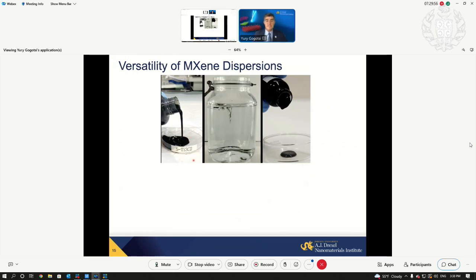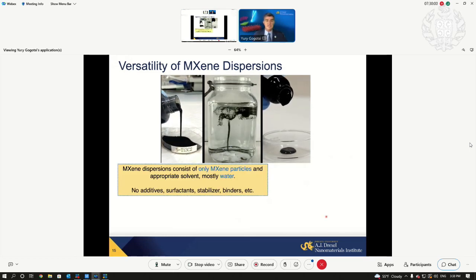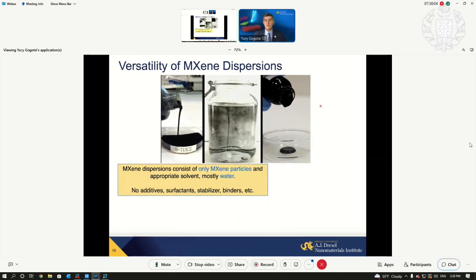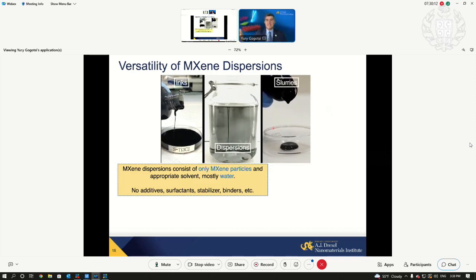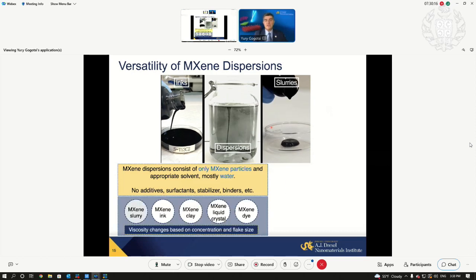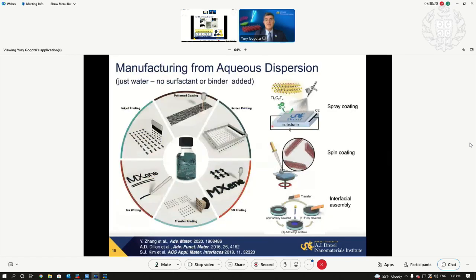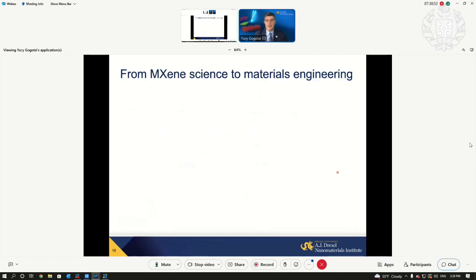And we can make it thin or thick, depending on what we want to do, whether we want to make ink for inkjet printing, for example, with this viscosity, or we can make a liquid crystalline solution to draw fibers out of it, or, for example, doctor blade a thick film on the surface. We can basically prepare any kind of dispersion. And we have control of material rheology. We can basically manufacture it by any known technique, 2D printing, 3D printing, screen printing, spray coating, spin coating, doctor blading, pretty much you name it here, interfacial assembly. What it means is that we can have a huge number of materials manufactured from abundant precursors, processable in large quantities even in the lab, and process it from pure water, no binder, no surfactant.